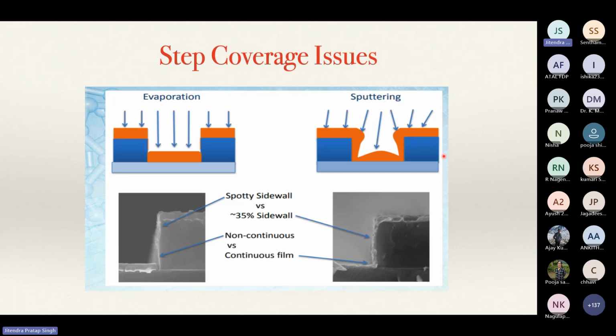Whereas in the case of sputtering, the point is that sputtering gets better step coverage, and the reason is that it uses a wider angular distribution. In sputtering, the ions are coming from all directions, hitting the target surface and transferring momentum, and to conserve the momentum the molecules also come out in different directions. Also, the atoms which come out from the target have high kinetic energy. Because of that high kinetic energy, the surface diffusion is also high in sputtering. So when you use the sputtering technique instead of normal thermal evaporation, we normally end up with continuous film formation. We do not suffer from the problem of the spotty sidewall, where the sidewalls are not coated with the film. So that is not there. This is one of the advantages of sputtering over evaporation.